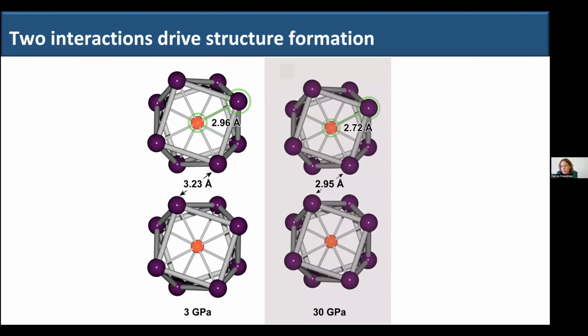And to us, this is a really interesting question: why does this structure form, and why do you have these iron bismuth bonds? We don't know the answer, but one potential hypothesis is that the iron bismuth bonds are formed not because of the stability of the iron bismuth interaction, but rather because a bismuth-bismuth interaction stabilizes the formation of this structure. This bismuth-bismuth interaction, denoted in the 30 GPa structure, is actually shorter than the double bond in certain dibismuth molecules, which are an interesting analog for a lot of the bismuth chemistry.